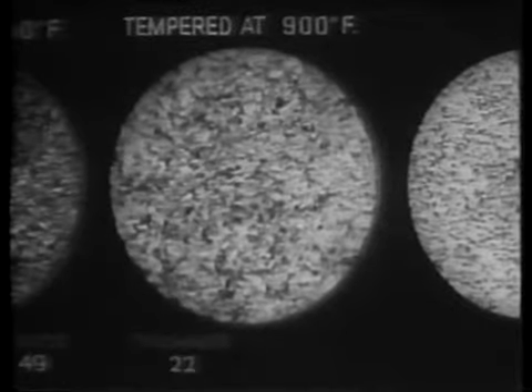Tempering at 900 degrees produces a further precipitation of carbide from the martensite. These carbide particles, diffused in the martensitic structure, are beginning to coalesce. Now the steel's toughness has jumped to 22. Its hardness is down to 39.